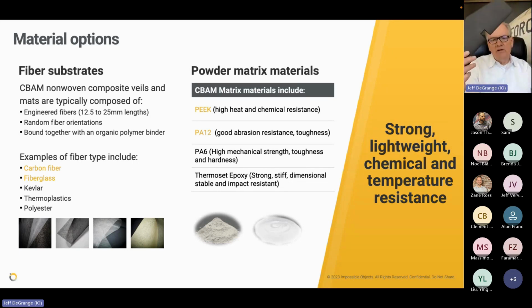And what I'm holding in my hand here, this is not ready for prime time, but this is now a unidirectional fiber sheet rather than a non-woven random dispersed surfacing veil. And we had to use a thermoset because it had to be low viscosity, because these unidirectional fiber sheets are very dense, and we need the material to flow and wet out these fiber sheets. And the big deal here is that this is 600 megapascal strength property with close to 50% fiber volume content. And it puts us into that first range of doing structural parts made with traditional composite fabrication techniques.